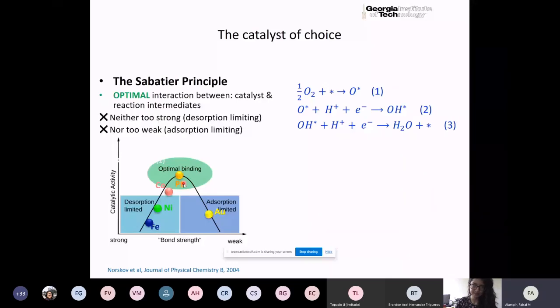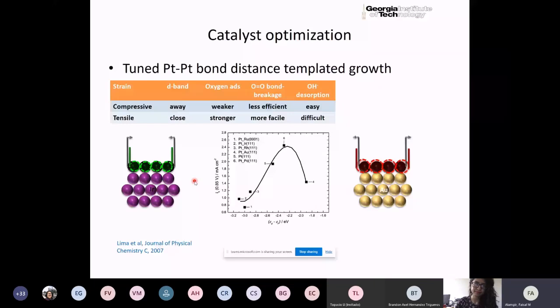It turns out that one of the best catalysts for the oxygen reduction reaction is platinum, and this is just in comparison to the other pure metals, but it later was discovered that some alloys of platinum with other materials can actually be even better. So the issue is that this alloying, if we actually want to have platinum combined with another metal, then that automatically incorporates two effects. It incorporates the charge transfer effect, that is the amount of electronic coupling that's happening between platinum and, let's say, the supporting material, supporting metal, or the alloyed metal. That's what we would call the ligand effect or the electronic effect. But together with that, there's the strain effect.